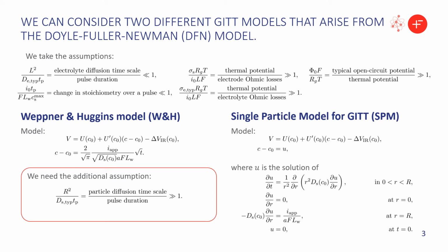But on the other hand, if we don't take that assumption, well, we can just have a very similar model, but now this variation in concentration, which here we call U just for simplicity, comes from solving this diffusion equation in the particle. That's why it's a single particle type model. And the interesting thing here is that note that the diffusion coefficient is evaluated at the C naught, which is the initial concentration at the pulse, which means that the diffusion coefficient can change across pulses, but within a pulse, we take it to be constant. And that's why we're able to use this technique that uses linear diffusion even to estimate variable diffusion coefficients.